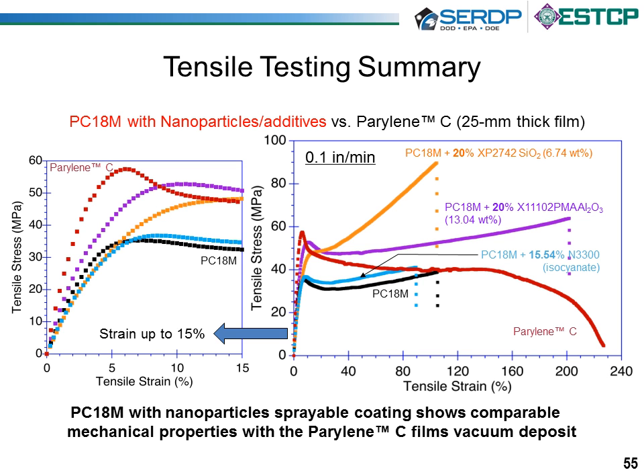And so as we go through, we took a look at a number of... the PC18M was the first material that we evaluated, and we took a look at a number of the different loadings of the nanosilica and the nanoalumina, and we compared it with Parylene C. Parylene C, that's the Cadillac of coatings. It's a very, very robust coating. It's been in use for a long time in specialized applications. It's vacuum deposited, which makes it a little pricier. The material itself is pricey.